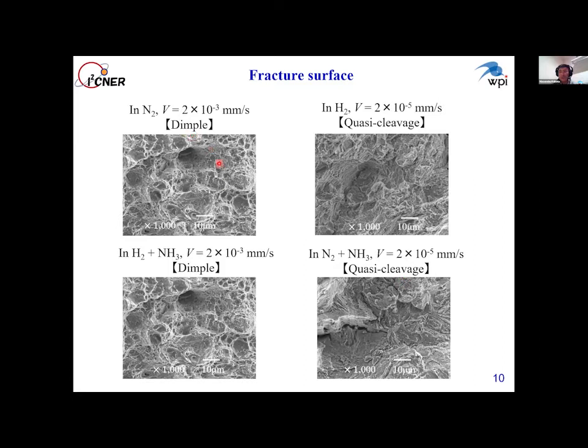In nitrogen, it shows dimple fracture surface. This is a representative feature that the material causes fracture in a ductile manner. The fracture surface in hydrogen shows quasi-cleavage. Hydrogen changed the way of crack propagation. Quasi-cleavage is also a representative feature of hydrogen embrittlement.